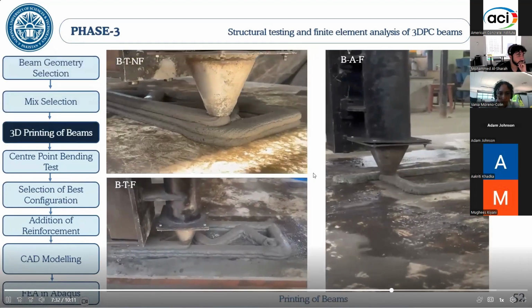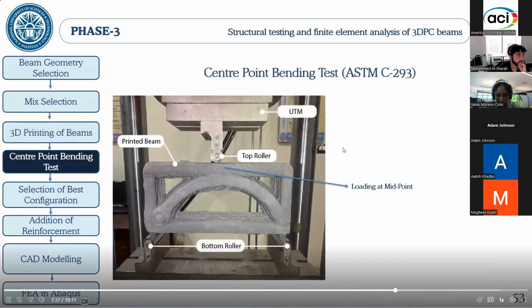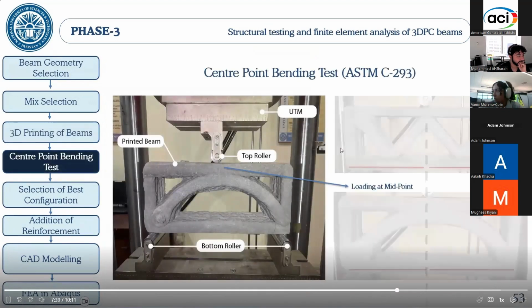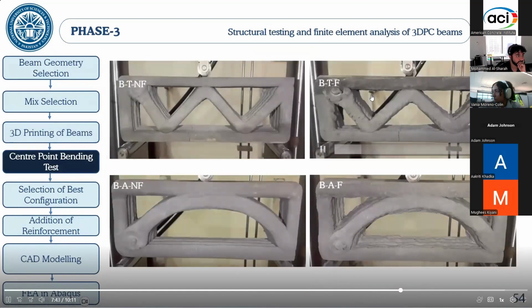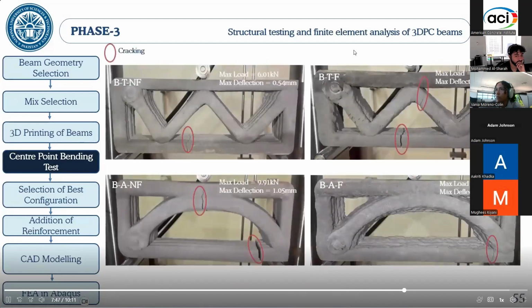Both the beams were printed using the M1 and the M2 mix. All the 4 beams were tested under the center point bending test, and the crack initiation was observed for all the 4 beams. Now, a common observance was that the cracks developed near the joints where the stress concentrations were high, mostly in the bottom fibers, and the fiber reinforced beams exhibited a ductile failure.